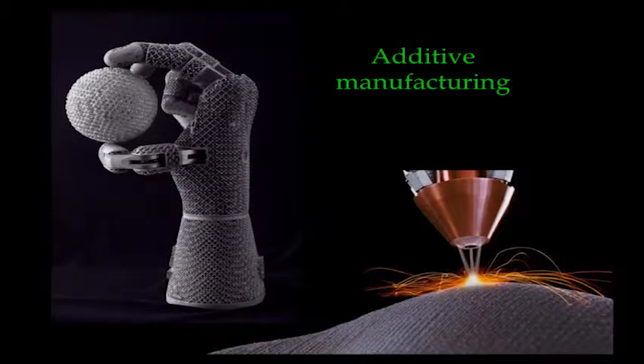So what's additive manufacturing? Well, it's a laser that's focusing an intense beam or set of beams onto titanium powder. And where it's focused, it actually melts the powder. And so by controlling where this beam is in three dimensions and in time, you can build structures. This is an example of a structure. You can build it from powder titanium with a computer-controlled laser. So this is an articulated hand holding a ball within a ball within a ball within a ball within a ball. All the balls are movable. You can make these structures now in additive machining. The titanium would go a long way to making these titanium parts by additive machining. Okay, it could really transform things.